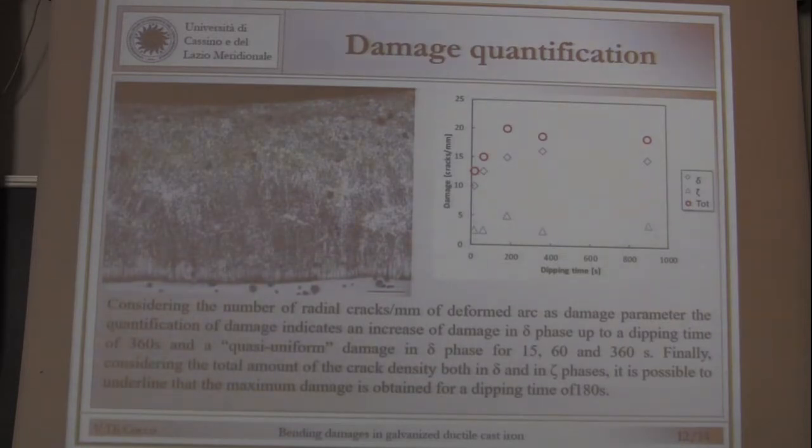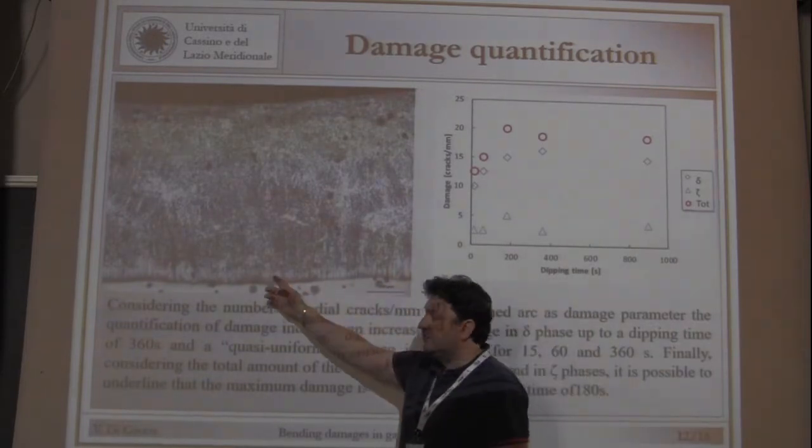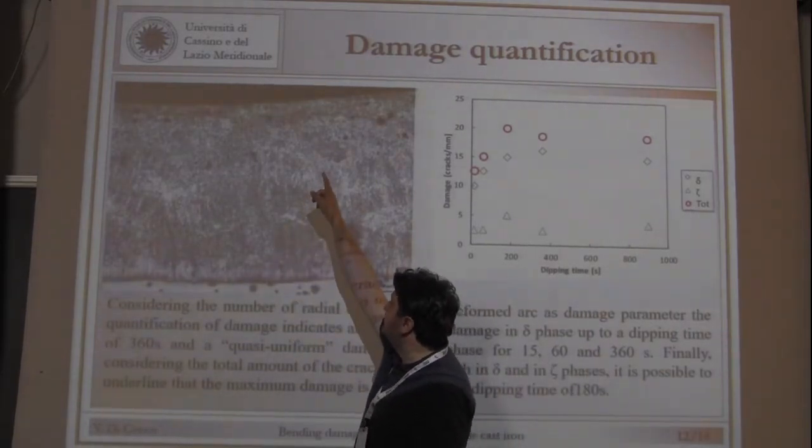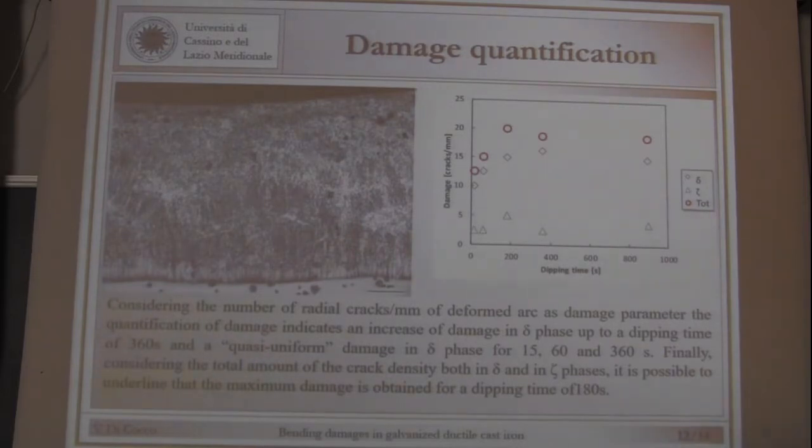It is important to underline that the damage is present inside the coating. The outer surface in this direction is not visible for the external check. This is a problem because if we use machines or components subjected to deformation, we can have damage of the coating inside. It is not so easy to check this kind of damage.